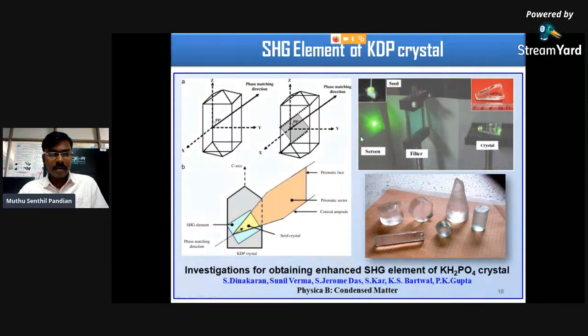So what we have done is we have cut the phase matchable direction alone. This 59 degree direction we have cut, and we have mounted it at the bottom of the glass sample, and we have poured the saturated KDP solution, and we apply different temperatures at the top and bottom portions. We have grown the crystal along its phase matching direction. This work was done in RRCAT Indore. We have reported this in Physica B, and this is an SHG directed KDP single crystal. This is KDP single crystals grown in our laboratory, SSN.